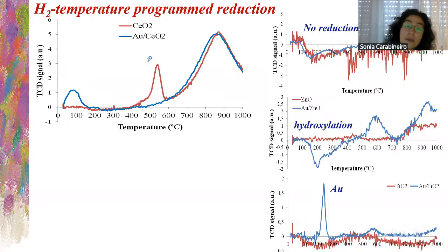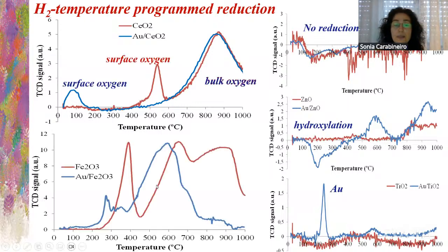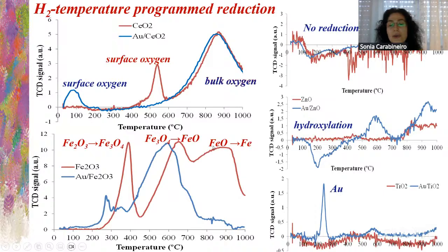But for cerium oxide, we already saw reduction of surface oxygen and bulk oxygen, and adding gold makes it occur at much lower temperatures. And for iron oxide, we see this reduction here. The first peak is reduction from Fe2O3 to Fe3O4. The second one is Fe3O4 to FeO, and the other one from FeO to Fe. If we add gold, then it occurs at lower temperatures.